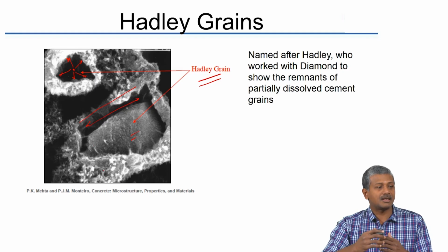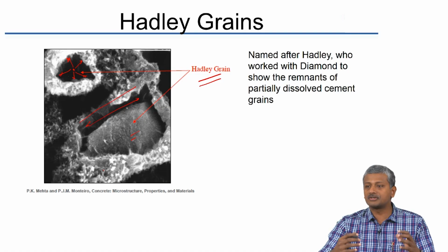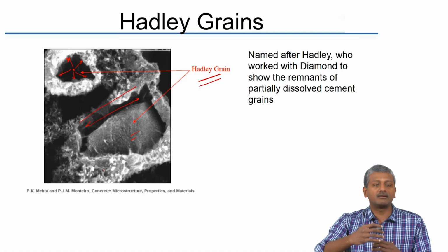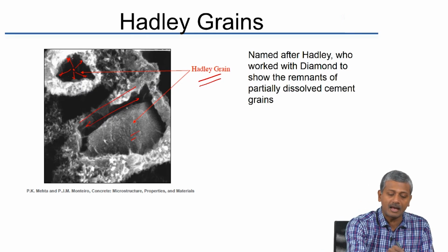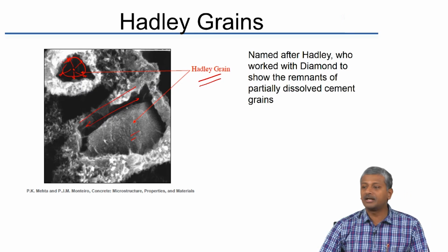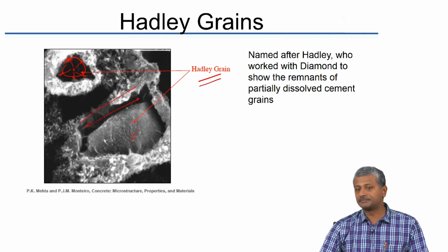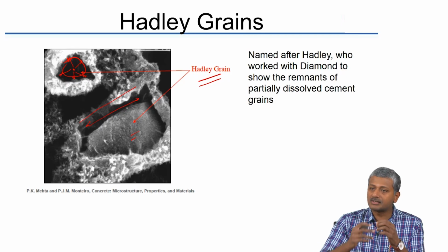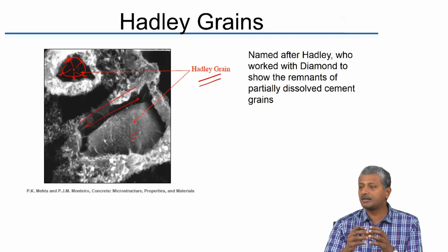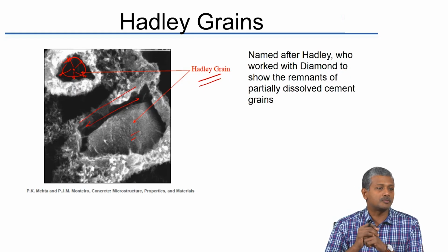So, that means that this grain is in the process of dissolution and producing the hydrates on the outer periphery. So, this gap is getting created, and in this case the gap is completely filled up the entire space where the grain used to be earlier. So, this must be true for smaller sized grains which are dissolving outwards and forming the hydrate products around and leaving behind an empty shell in the place where the grain used to be earlier.